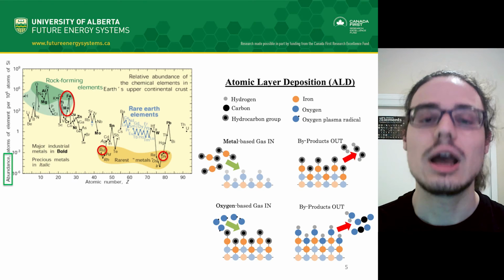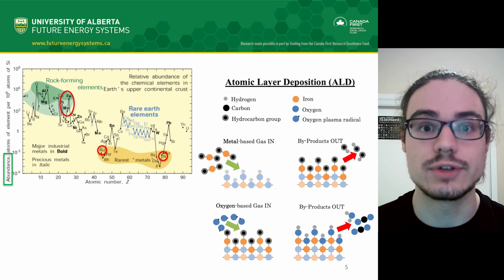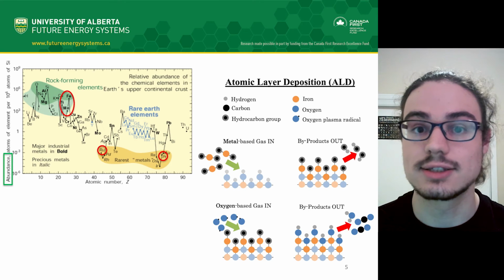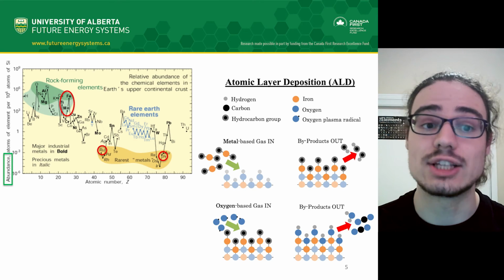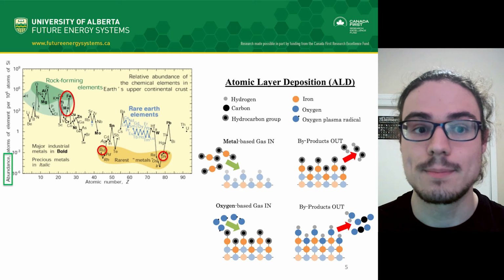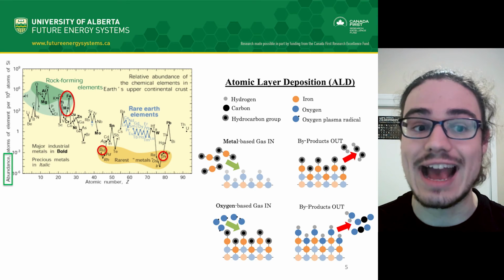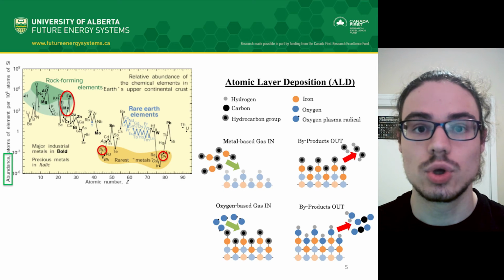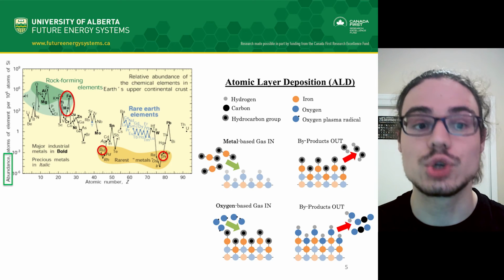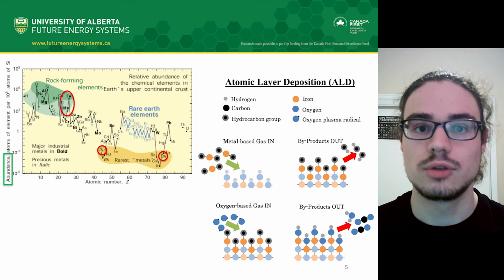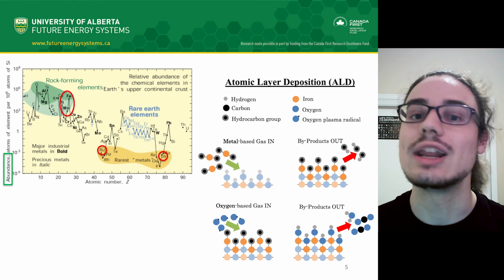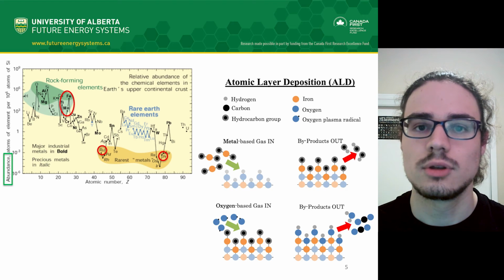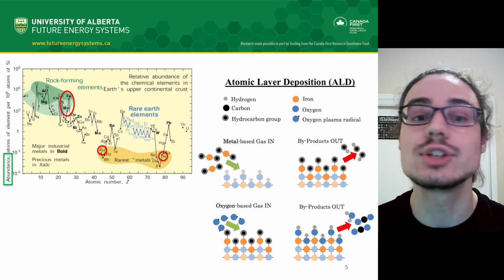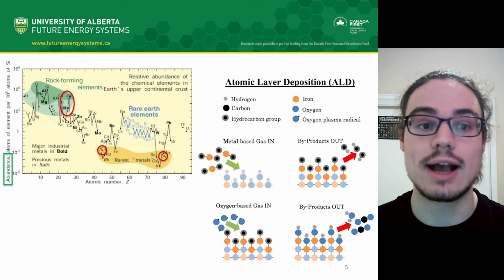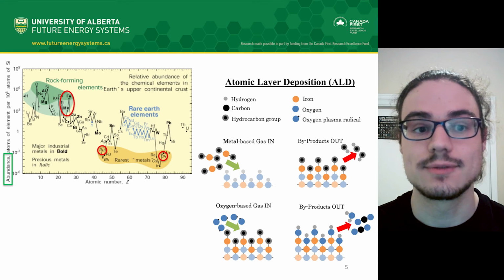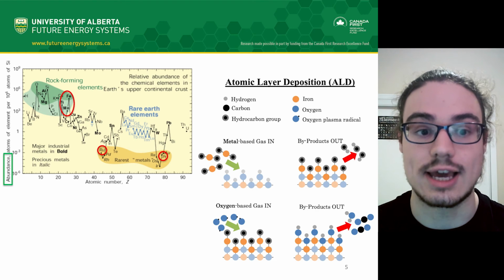In my research, I use atomic layer deposition, or ALD for short, to make nano-sized layers of these catalysts. I essentially grow the catalyst on the high surface area air electrode in a Zinc-Air battery. ALD works by using a metal-containing gas to deposit metal atoms onto the surface, which is then exposed to oxygen to create an atomic layer of metal oxide. This process is then repeated over and over again to create a thin film of metal oxide. The gases are able to move around and cover every surface of a high surface area electrode to maximize the total surface area of the final catalyst. And this will help get the most out of a low-cost catalyst.